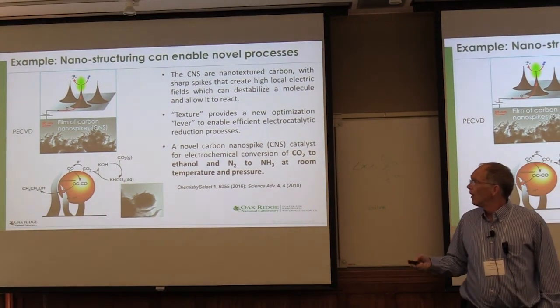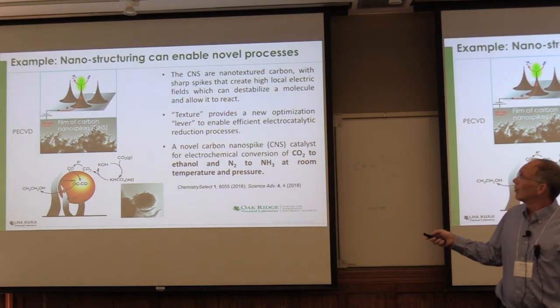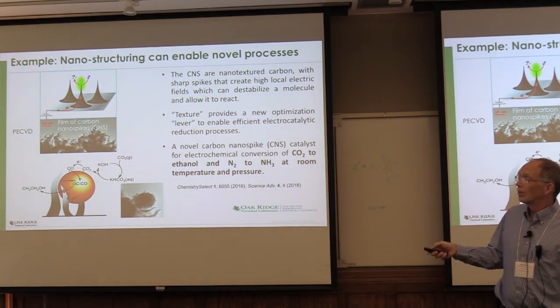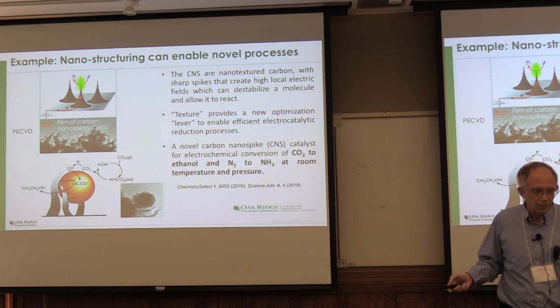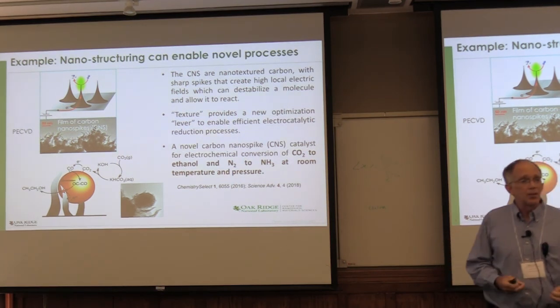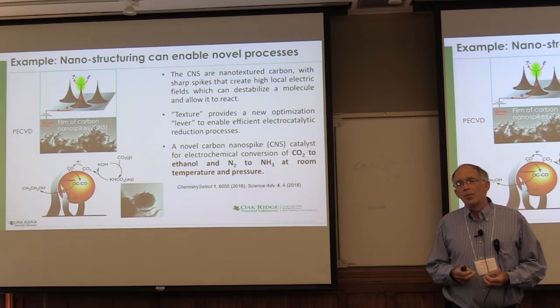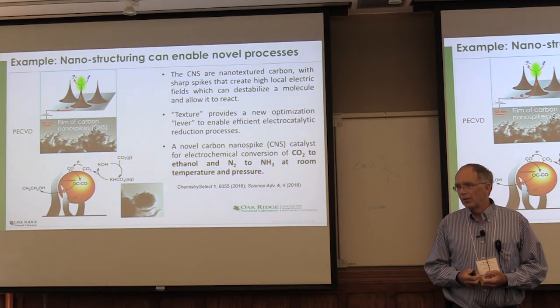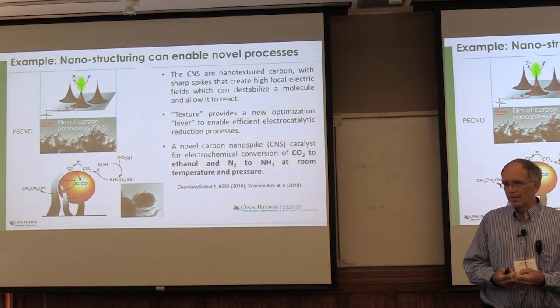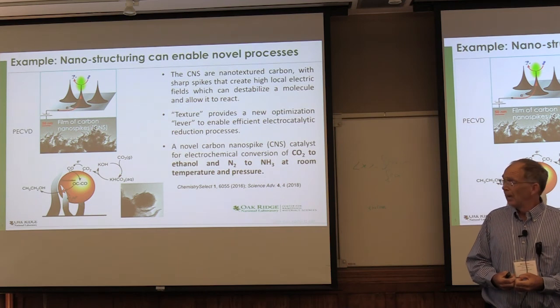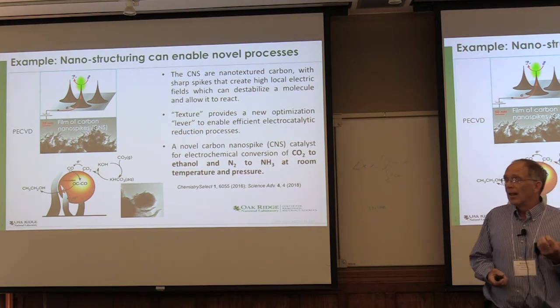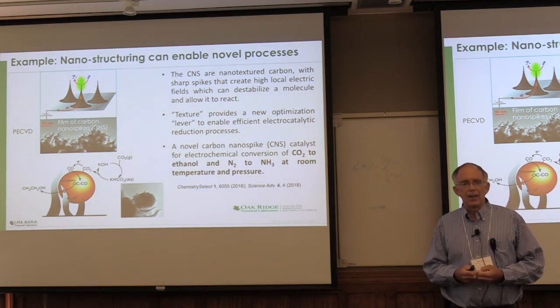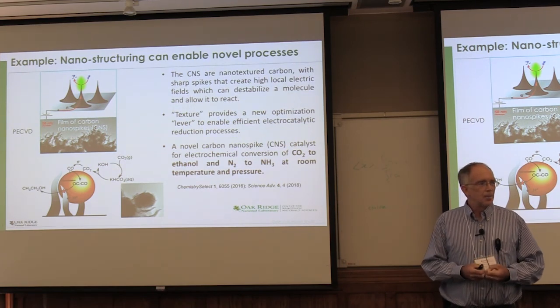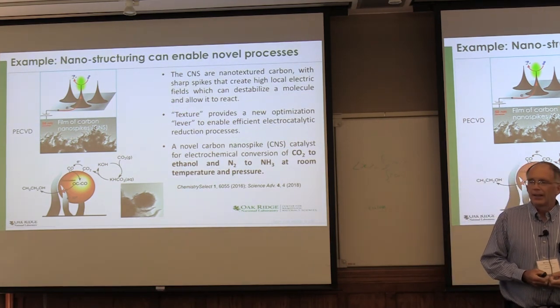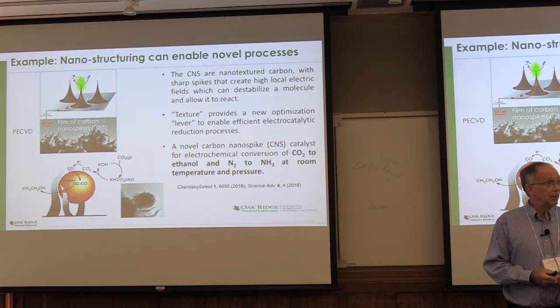gas into the electrochemical cell. When the nitrogen molecule comes close to one of these spikes, and it's basically always going to, because the whole surface is spikes, it weakens that nitrogen-nitrogen bond. So basically you're able to reduce the nitrogen molecule, which is a triple bond. It's really hard to break that bond, by the way, by this electric field driving it in a catalytic fashion. So this is a carbon-based material that can catalytically reduce about any molecular species that we've ever looked at. That's a pretty big deal.